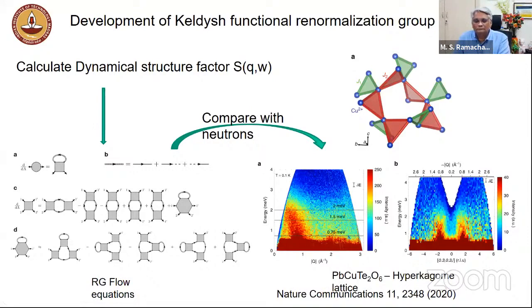And the dynamical spin structure factor calculations then allow for comparison with experimentally observed inelastic neutron scattering on these quantum materials. So the expectation is to provide a smoking gun signature of the exotic quantum spin liquid phase in 2- and 3-dimensional frustrated quantum magnets via signatures of emergent fractionalized quasi-particles.